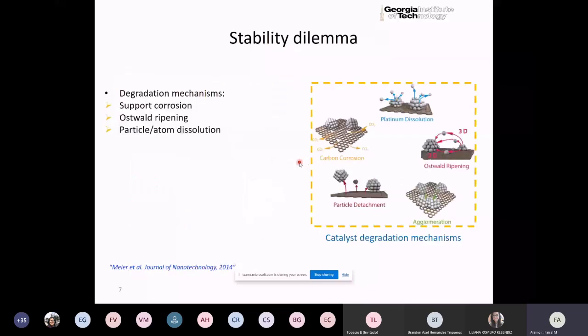On the other end, if you're looking at catalysis, the issue is often not really just about the activity of the catalyst. The activity of the catalyst is what we've been describing so far. How efficient is it in doing the reaction that it needs to do? The other part of a practical catalyst is that it also has to be stable over many cycles of that reaction. And in the case of these catalysts, the idea that has been fairly integrated into applications by now is that the size of the catalyst matters. The smaller the size of the catalyst, the larger is the surface area to volume. And if you have a large surface area to volume, then you have a large effective reaction surface.